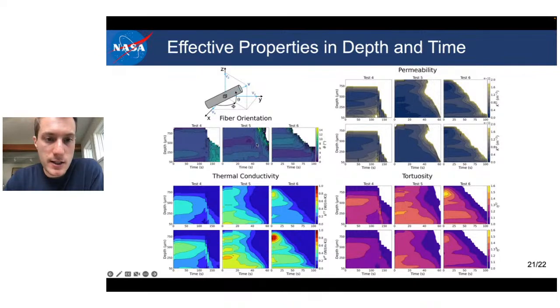We also ran a similar study for the fiber orientation, where we keep computing the fiber orientation throughout time, and we can track how the fiber orientation changes as the material oxidizes. Of course, you can see pretty clearly that there is a correlation between your material properties and the fiber orientation that is changing. But it's very interesting to see that we can capture, for example, the fibers compacting as they collapse with each other, which is when you see these bright colors. Or you can see the fibers pull up, which is also these bright colors for the orientation.